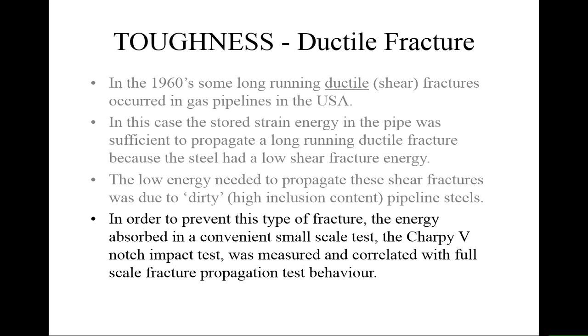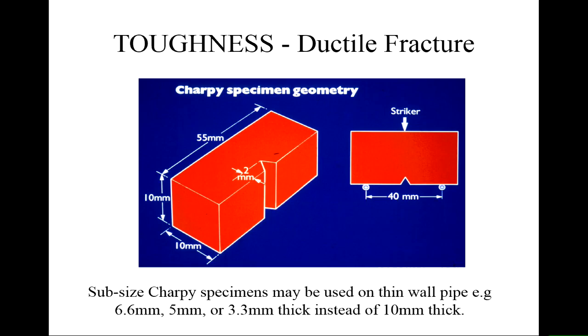So, of course, you need a convenient test to make sure that your material will pass this, and the Charpy V-notch test, or the Charpy test, which can easily be correlated with full-scale fracture propagation tests on pipes, has been used as a way to say, we need this amount of Charpy energy from this simple test. And a Charpy test takes about 10 seconds to do. The making of the sample takes a bit longer, but it's a very easy test, and because it's easy, it's quite reliable to use for development processes and quality monitoring.